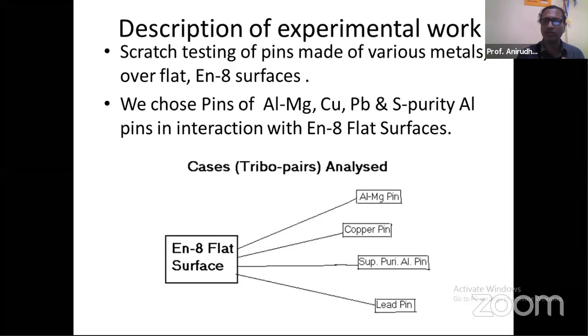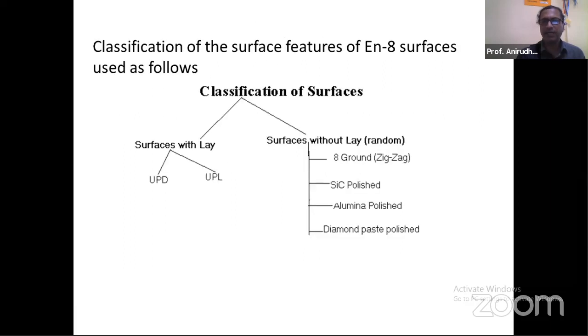So Lancy generated different surface features for these flat surfaces. We will see that he developed surfaces which belong to 2 different categories: one called surfaces with lay, and the other without lay. That means one category exhibited some kind of waviness, called surfaces possessing lay, and those surfaces which did not have any waviness, which were random, were called surfaces without lay, or random. Lancy did those experiments, and I was the man who investigated the surface features and correlated them with his experiments.